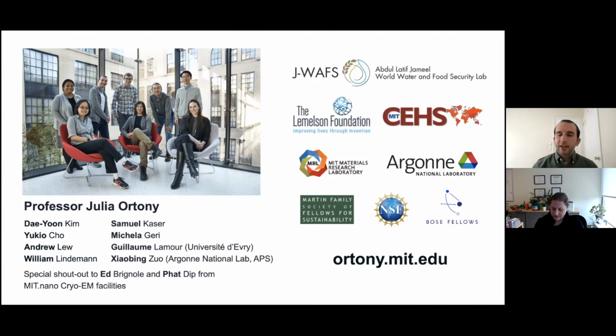Yeah, that's a really interesting question, and also an area of research for us. I had previously hypothesized that simply by changing the pH, we might be able to disrupt the interactions between these chelating head groups and the lead to effectively recharge the nanofibers. But as you saw, even in the cases where the head groups are mostly or fully protonated, they still have the capacity to remediate lead from water. So in that case, it doesn't seem like we can fully recharge the head groups and use them again.